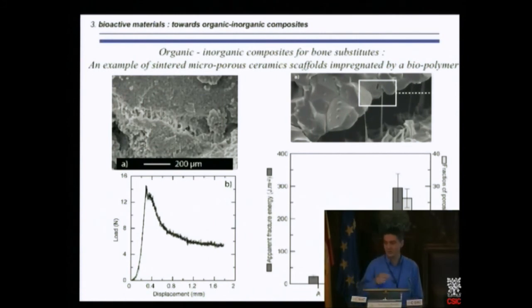What are these bridges? This is the organic matter. So we have some organic fibrils that act to resist crack propagation. So we have an inorganic, organic composite, and when a crack or microcrack propagates, you have bridging by these fibrils, like in bone. In bone, you have collagen that is able to bridge microcracks in the mineral phase.